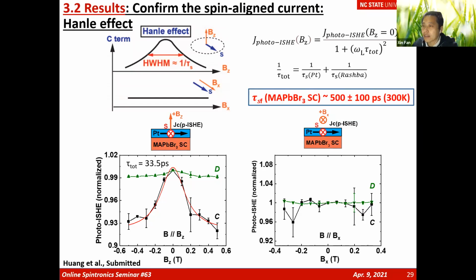I see. On a related point, have you tried the Hanle effect when you apply a magnetic field in the Y direction, BY? Will that behave the same as BZ? We didn't try BY, but we tried BX. BX means the magnetic field and the spin polarization we generate are parallel, and we don't see a significant change when they are parallel to each other, as in the right corner figures. But if you do BY, do you expect the same as BZ? I would expect it to be more or less like the BZ direction, if it is still perpendicular to the spin, right? Yes. I see. Thank you.